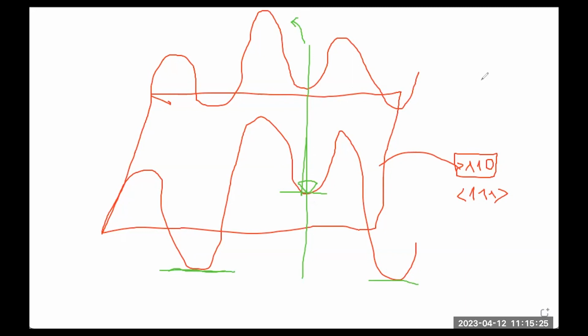You just increase stress again and again constantly till maybe 400 megapascals, 500 megapascals, and with thermal activation, you first activate the middle part of this screw dislocation. So this middle part will go to the top. So it will have something like this. Suppose you don't see this part. Then this part goes to the lower energy state. You form this kink, what we call a kink, and this part goes to the lower energy state.